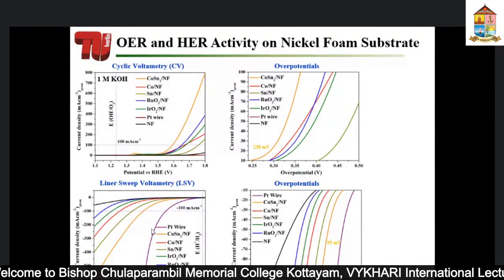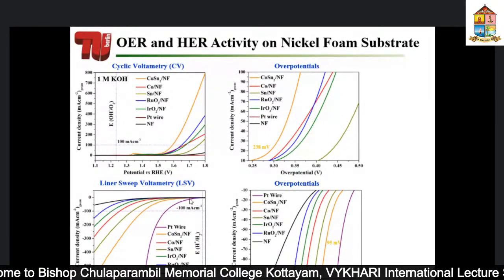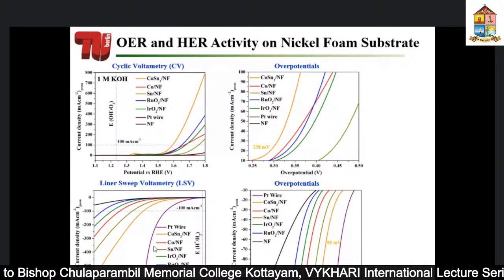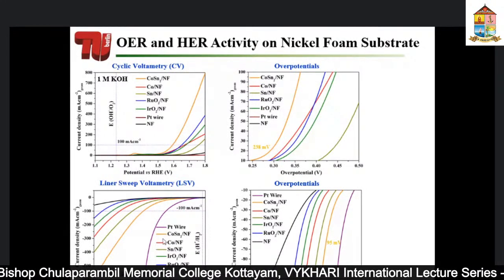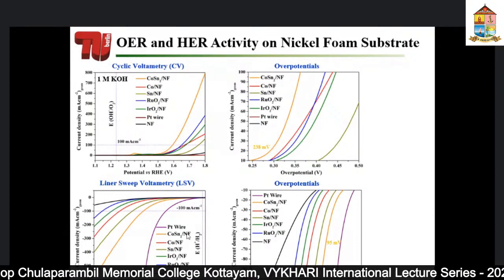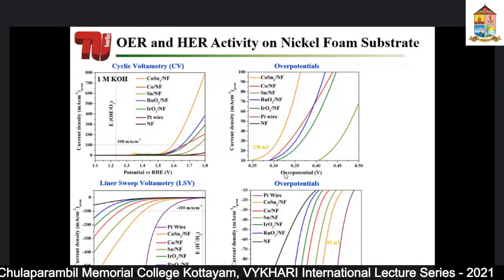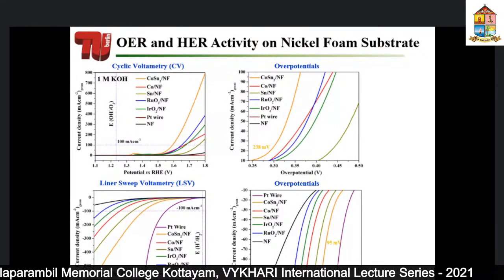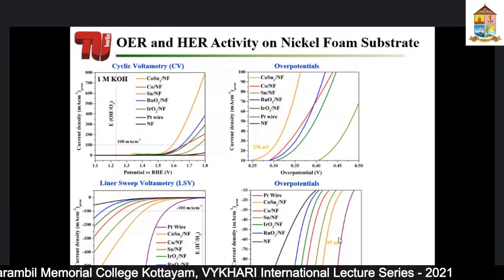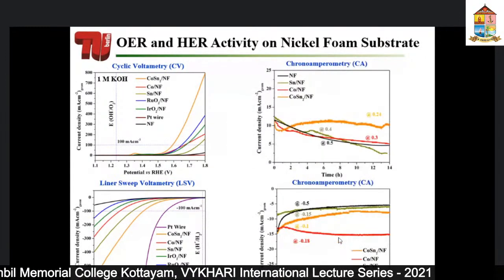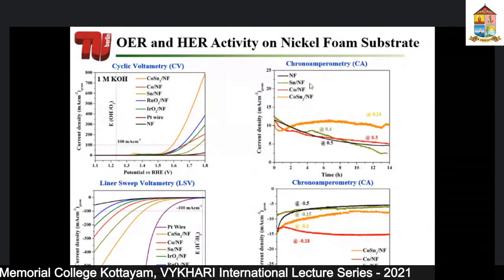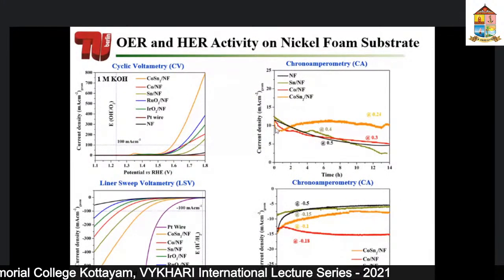And we also check the hydrogen evolution reaction, and what is also clear from here is that we have a better overpotential. This is the overpotential, 230 and 95, which is quite good compared to the literature reports. And stability, as you could see, if you take only tin and only cobalt, they are poor. But if you make cobalt tin, they are excellent.